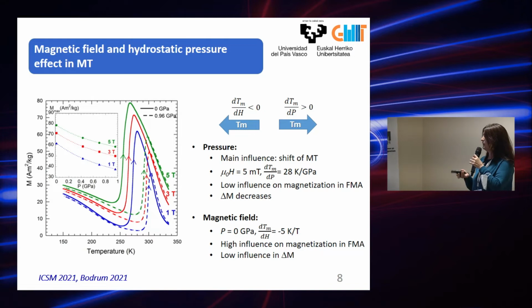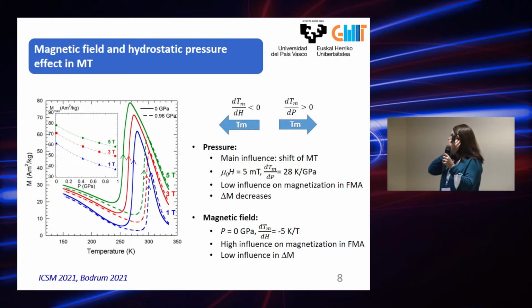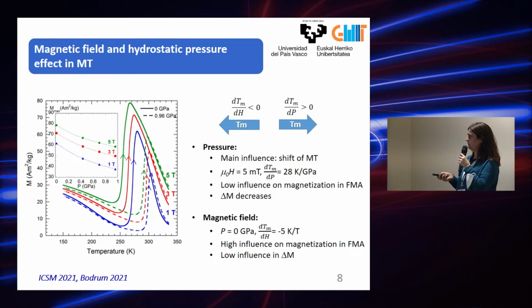Okay, what is the effect of the combination of the magnetic field and hydrostatic pressure? So in this case, we have opposite influence. We can see the continuous line is at zero pressure, and then we have this discontinuous line that is the effect of the pressure at different magnetic fields. So in this case, the pressure shifts the temperature to high temperatures, but the magnetic field goes down. So we have a combination at the end.